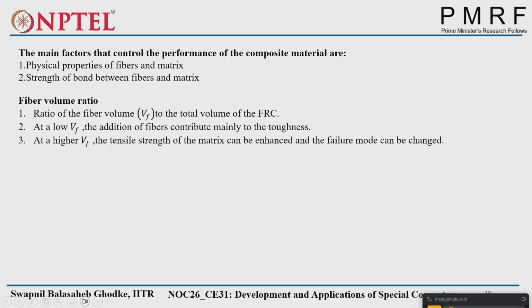Another aspect is the fiber volume ratio. If the fiber volume is low, moderate, or higher, that also affects the properties of the concrete matrix. So, what is the fiber volume? It is the ratio of the fiber volume VF to the total volume of the FRC, that is, fiber reinforced concrete. At low VF, fiber volume, the addition of fibers contributes mainly to the toughness. And at a higher VF, the tensile strength of the matrix can be enhanced and the failure mode can be changed. So how low and how high the value is, we'll see in the next slide.